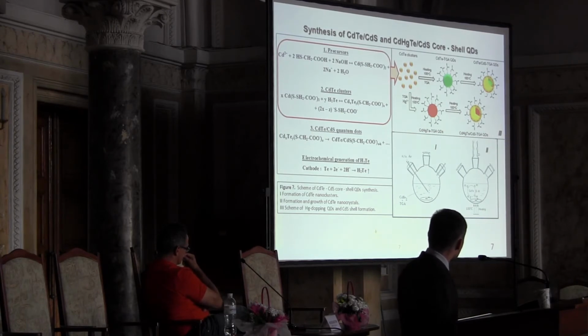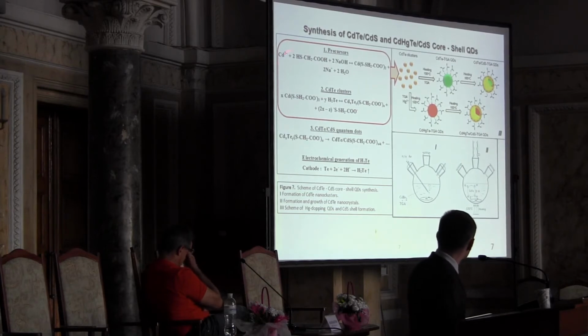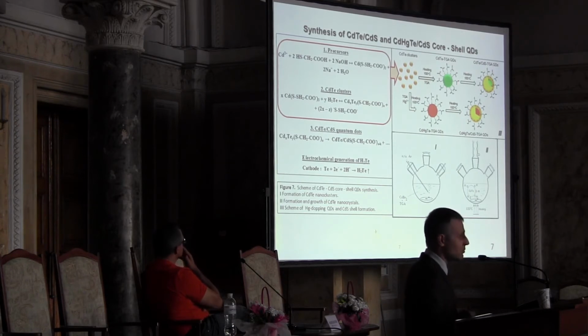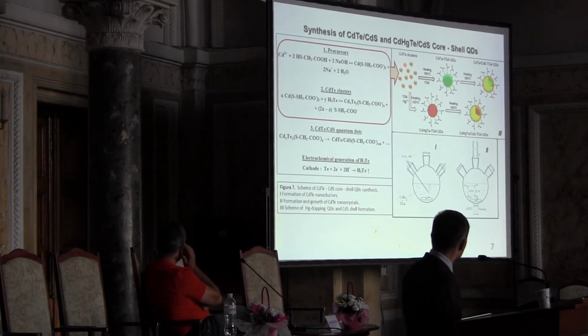And this kind of synthesis is good because if you want to dope your material, if you want to add some other chemicals to it, you can do it at different steps. You can either add it at the level of mixing of the components, or you can add it to clusters, or you can add it during growth, or you can actually stop the growth and add it afterwards. It depends on your desire, ideas, and so on. And here you can see the step, for example, of mercury doping, where you add the mercury ions to the clusters, and then when you start to grow, it already creates cadmium mercury telluride particles stabilized.